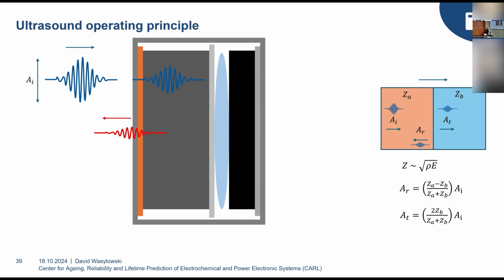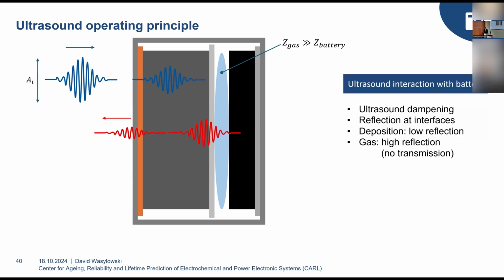And this last example is a gas accumulation that I showed you earlier. And gases have very different properties than both liquids and solid materials. In fact, they have a very much higher acoustic impedance than all of the other materials within our battery. So we will not get any transmission at all, but only a very large reflection. And this is also true if we would now introduce a deposit underneath this gas accumulation. So because this gas is reflecting all of the sound wave, we are not able to interact with this deposit underneath this gas accumulation in any way.